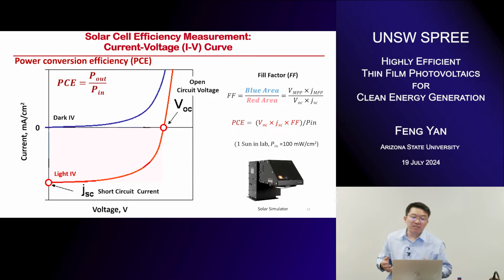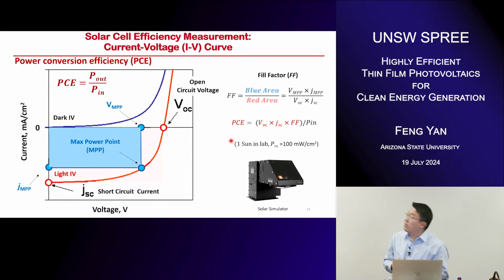Measuring the IV curve is one of the dominant techniques to determine the power conversion efficiency. Traditionally, we use current and voltage to determine the open circuit voltage, and also, let me open the laser pointer, the short circuit current. This is a very simple way to determine the power conversion efficiency by determining the voltage and the current. Meanwhile, if we check this blue box and pink box, we can determine the fill factor. So this is how we determine the power conversion efficiency for all the PV techniques.